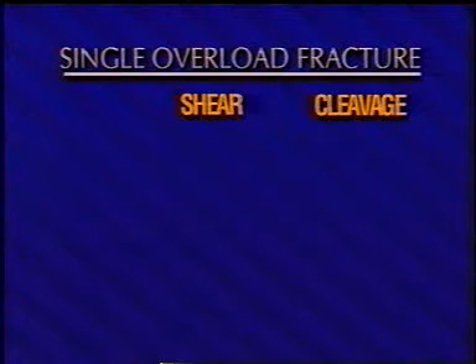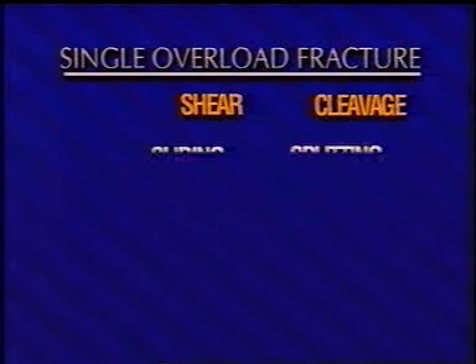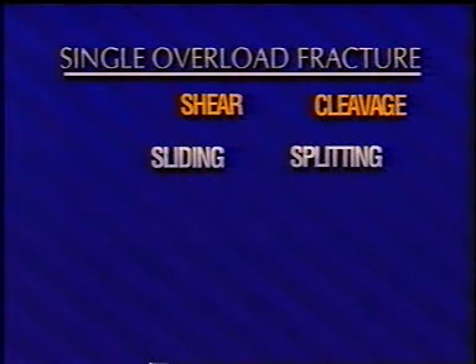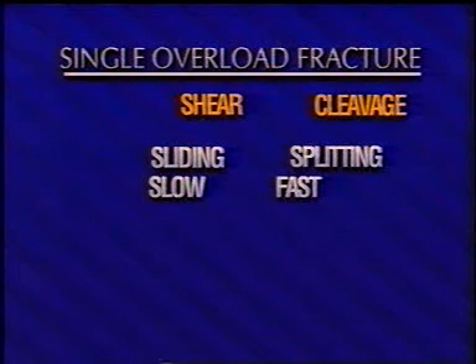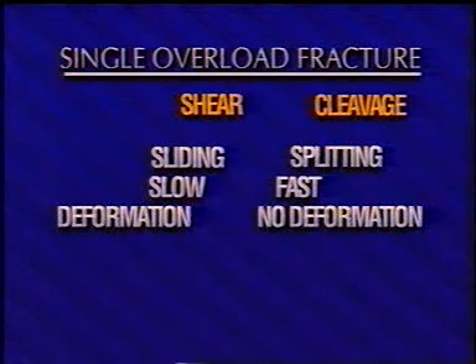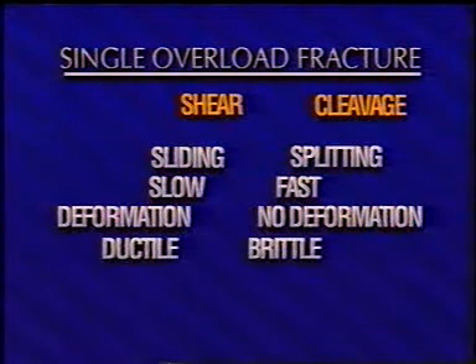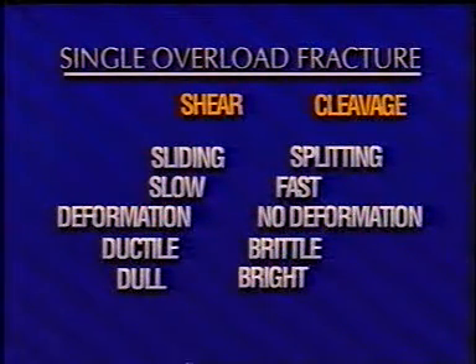Shear and cleavage are quite different in many ways. The movement of shear is sliding. The movement of cleavage, splitting. The rate of fracture in shear is generally slower. In cleavage, faster. With shear, there is deformation. With cleavage, no deformation. Shear is typical of ductile metals, cleavage of brittle metals. Generally, a tensile fracture that has sheared appears dull and fibrous. Cleavage fracture is usually bright and sparkling.